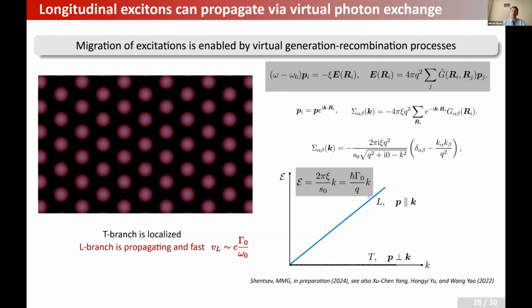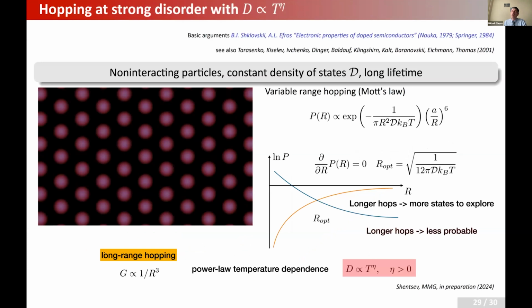And then it turns out that even if the excitons are localized in these moiré lattices, some of these longitudinal excitons can propagate. And then, depending on the disorder, you can imagine different scenarios. For instance, in that case you can have a hopping transport, say phonon-assisted, but with a diffusion coefficient which is proportional to some power of the temperature, a power-law temperature dependence rather than an exponential one. And this is just because of the long-range hopping in that case, because the coupling between sites decays like 1 over r cubed. This is the dipole-dipole coupling I have mentioned as the origin of the effect.